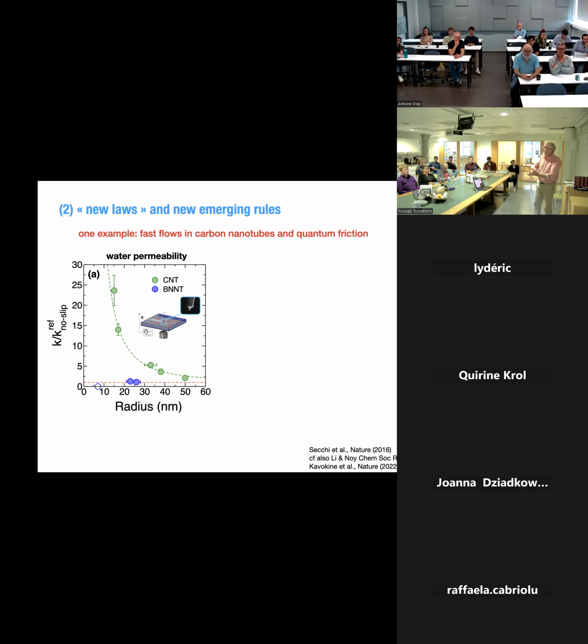Another perspective about what to expect at nanoscales is that sometimes you see new laws, new behaviors that you wouldn't expect at all. Again, I will be very quick on that, but these are experiments that we did 10 years ago, where we looked at the permeability, so really how much flux of water under a given pressure, in a single nanotube. The idea was to probe it in a very controlled way. We had to use a trick to measure it, but I skip all these details. What was very surprising is that the permeability of the carbon is much larger than what you would expect with a no-slip boundary condition, meaning the classical Hagen-Poiseuille law.